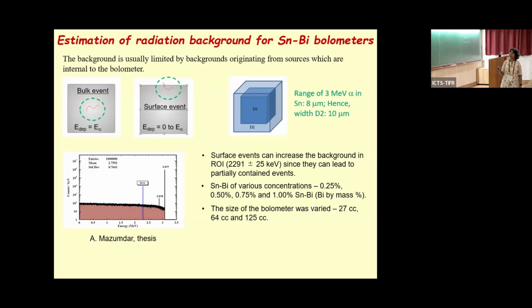If the event happens inside the detector, full alpha energy is deposited. But if the event happens close to the surface, only partial energy gets deposited, and then it will come in your region of interest. So this is shown for this bismuth, that you will have either 3 MeV alpha or 2 MeV, but if the alphas are emitted close to the surface, then that will generate the background in the region of interest.